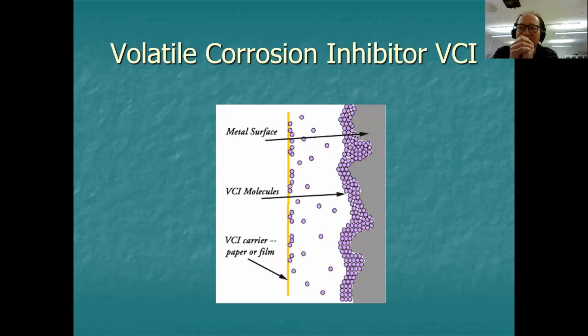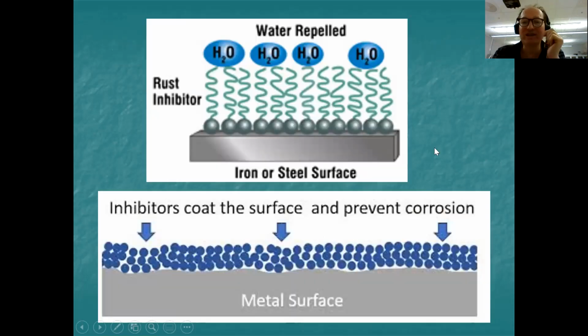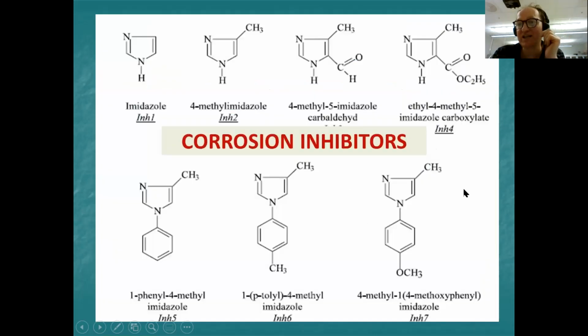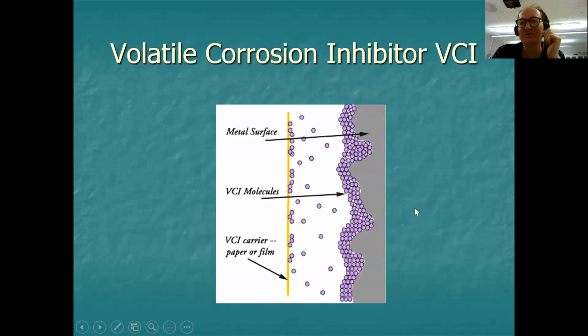So going back to the concrete again, one of the ways which has turned out to be very popular for protecting concrete, and in particular the rebars in the concrete, is to use a volatile corrosion inhibitor, otherwise known as a VCI, a volatile corrosion inhibitor. What does that mean? Well, we take an organic compound like one of these, for example, which has a finite vapor pressure. So these are chosen on purpose to be volatile, meaning that if you leave them on the table, they eventually evaporate. And the idea is we do that. We create a situation where we can evaporate, in other words, put into the vapor phase, the corrosion inhibitor.